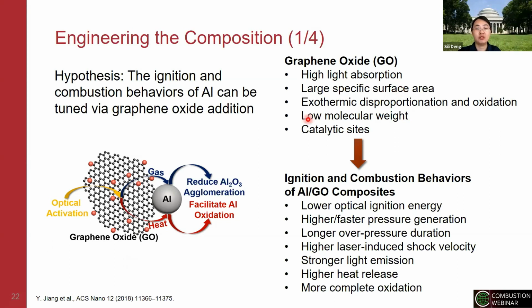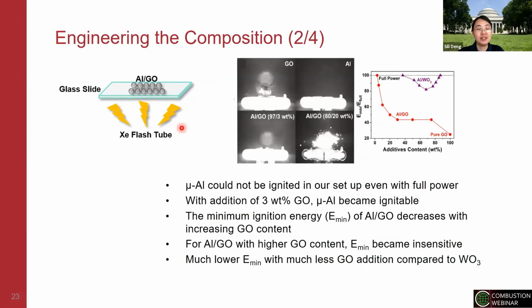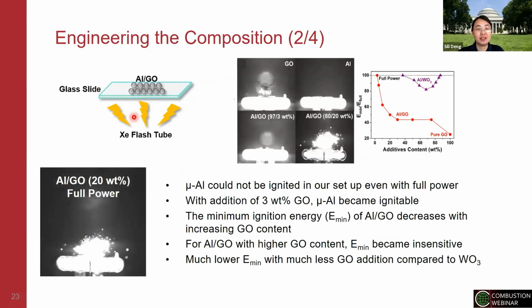And of course, the 2D materials have a relatively large specific surface area. And specifically with the GO, it has the disproportionation reactions upon the flash ignition, which is exothermic. So it can contribute to the ignition energy of the energetic materials of aluminum that we are interested in. So we expect to see that with the addition of a graphene oxide, the ignition and combustion behavior of aluminum can be enhanced. And we test our hypothesis in this flash ignition apparatus. So we have a flash tube and we have a glass slide put on that, and the particles will get just loosely put on top of the glass slide.